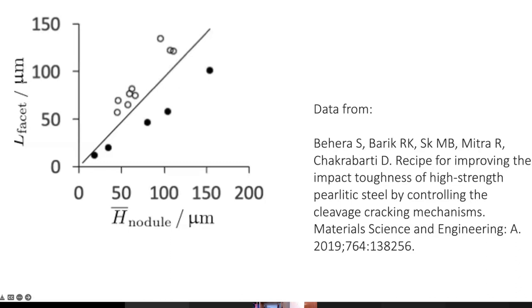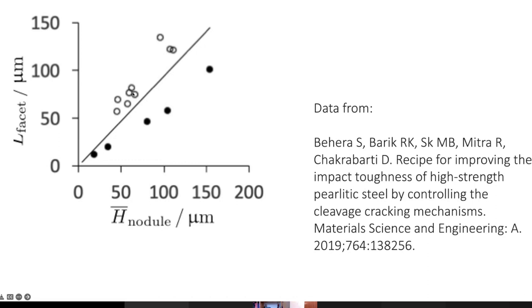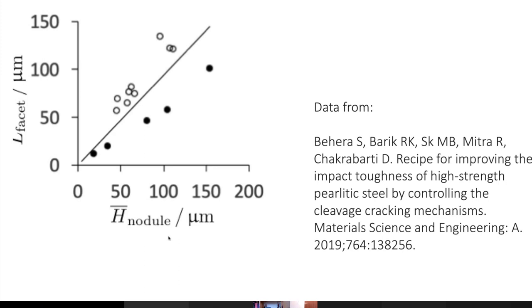This means that the toughness of pearlite really depends on the size of the nodule rather than on the interlamellar spacing, because if you are talking about cleavage fracture you need to deflect a cleavage crack frequently as it progresses. If the nodule is essentially a bi-crystal, there isn't much deflection of the crack by the lamellar structure. The unit of fracture is the nodule, and there is a strong correlation between the cleavage fracture facet size and the pearlite nodule size because the crystallography within a nodule is quite uniform.